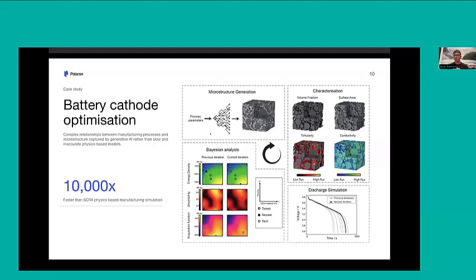We can then extract properties from the structure that allow us to simulate the performance. In this case, we're doing an electrochemical simulation of a lithium-ion battery cathode. So we can predict how that cathode would behave as we do an electrochemical charge or discharge. And then we can do a Bayesian optimization analysis where we search the space of possible process parameters and then identify the process parameters that give us the structure with the properties that give us the best discharge simulation. And so in under a day, we managed to identify an optimal process parameters pair that gave us a performance that was actually a 10% increase on the original design that we had.